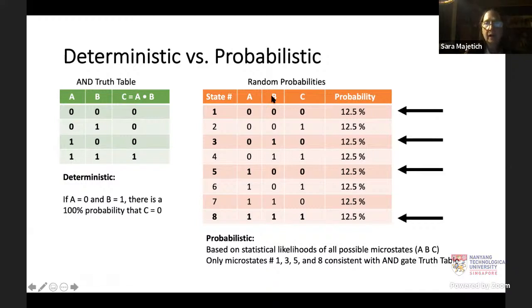If you have these 3 superparamagnetic tunnel junctions representing A, B, and C, you really have 8 microstates, and each of them are going to be equally probable. 4 of those microstates are consistent with the AND gate truth table, and 4 of them aren't. So the strategy in how you hook up these devices with each other is in such a way that you're going to favor the 4 microstates that are consistent with the desired truth table at the expense of the others.